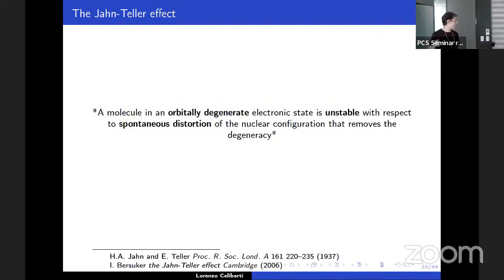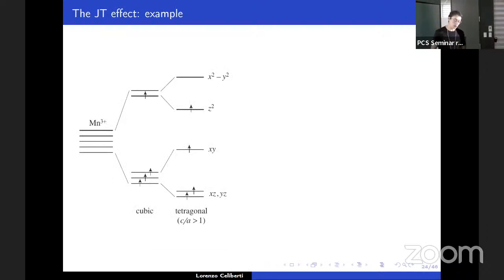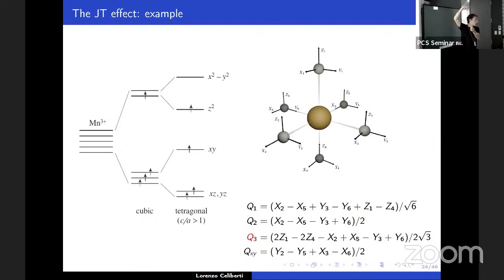So at this point, I guess everyone knows what the Jahn-Teller theorem is. You have orbital degeneracy, which is unstable with respect to lattice distortions, and therefore you expect that some distortion takes place and you reduce the energy of your system. This is an example of what can happen on the multiplet level structure of our material. In this case, you have a manganese 3+ ion. You have the splitting of the t2g and eg of the crystal field, which is further split by this tetragonal distortion, which basically means that you, for example, compress on one axis the octahedron and expand on the plane, or vice versa. And here you have the definition of some modes: the breathing mode Q1, orthorhombic, tetragonal, and one trigonal mode, with respect to the coordinates of, for example, the oxygen.